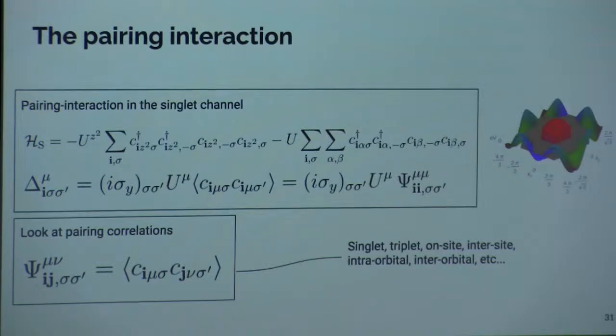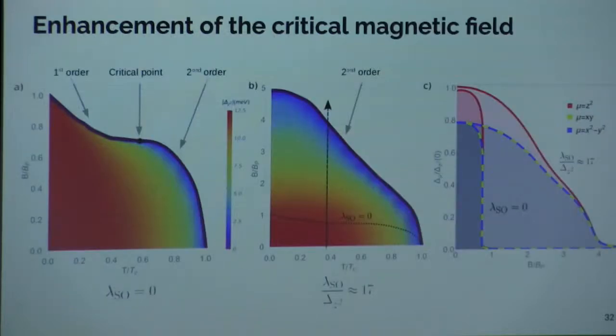After solving this, we also can look at all the pairing correlations. And these will be very exotic. In there, we can have singlet, triplet, on-site, intersite, interorbital, everything. Of course, we do reproduce the enhancement of the critical field. So in the middle figure, the dotted line shows the case without spin-orbit coupling, and the solid line shows the case with spin-orbit coupling. So we see the enhancement.